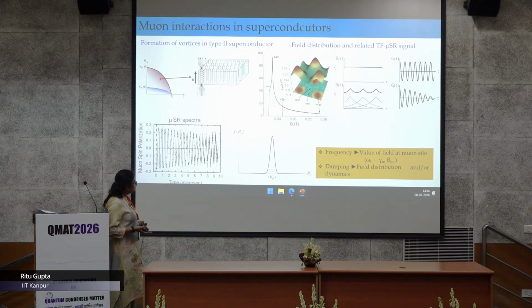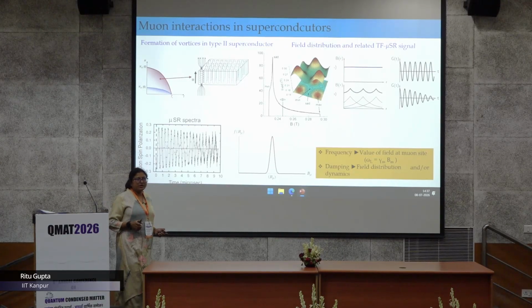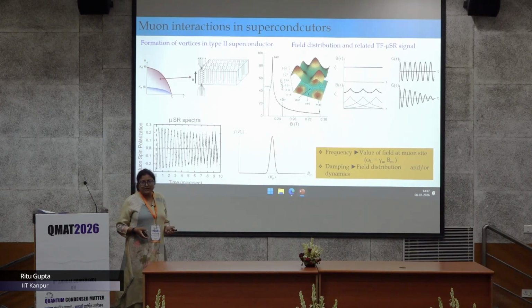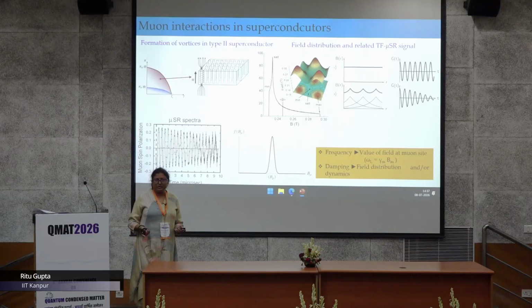So if you look at the peak position, this will give you the frequency, the value of the field which is experienced by the muon, and the damping in this peak will tell you about the field distribution or dynamics in the system. So basically, in a superconductor, the width of this peak is directly related to the inverse square magnetic penetration depth, or I can say the superfluid density.